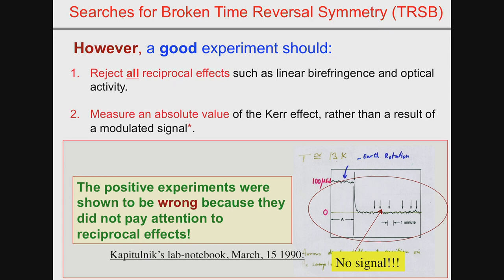And then when the high-temperature superconductors that were supposed to produce many milliradians, here I calibrated it at 100 microradian to within 1 microradian, if you want. This is zero. Showed nothing.